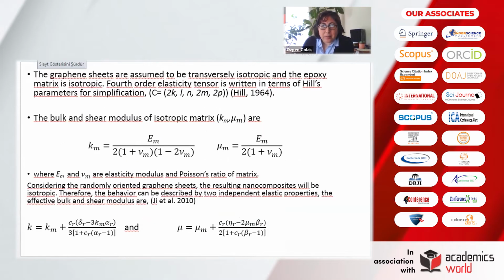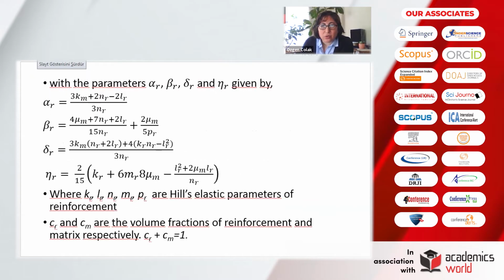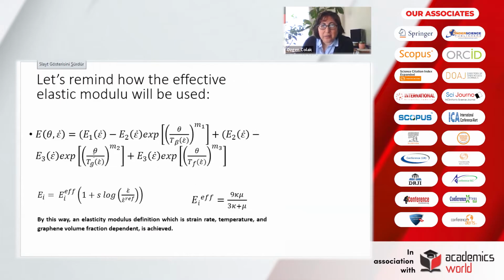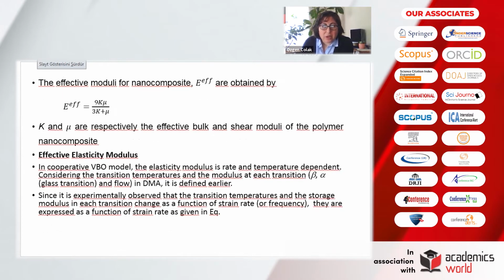These are some bulk and shear modulus for the matrix and some other parameters related to Hill parameters, etc. And basically, if I remind you, this was the elasticity modulus, which was valid for polymeric materials. After using the Mori-Tanaka scheme, the effective elasticity modulus is defined considering the formulation that is given before. And these are some more formulations.